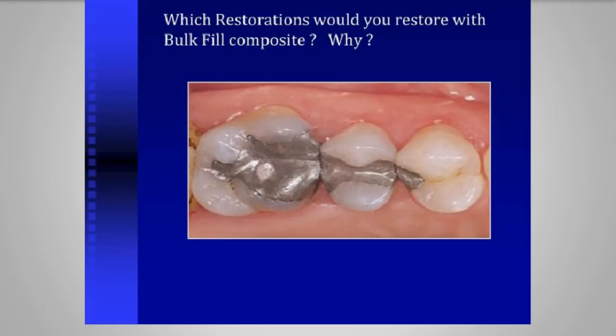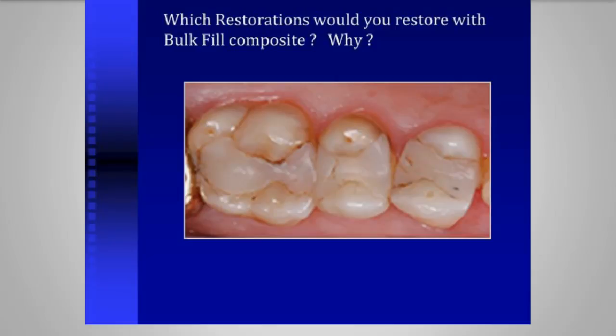When we look at something like this, we've all seen it in our practices when we get these MOD buccal linguals and in your underneath cusps and everything. I'm going to ask you now, unless you're using glass ionomer, which is still used in my practice, this could be one for bulk fill dual cure, because you're going to have less stress in the box, get some good contacts. This is a tooth that you'd probably want to use bulk filling for, especially dual cure.